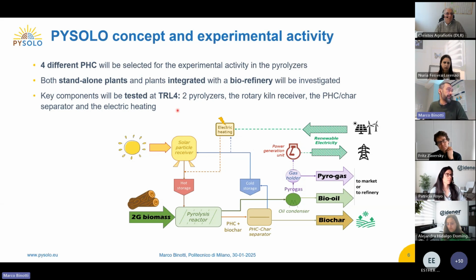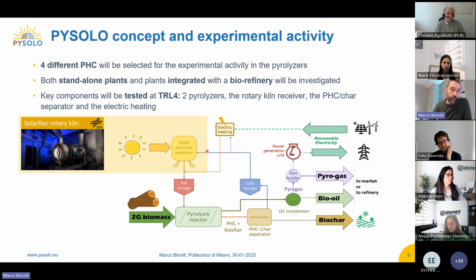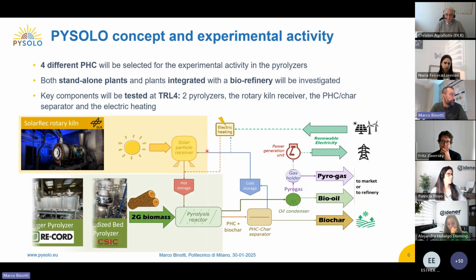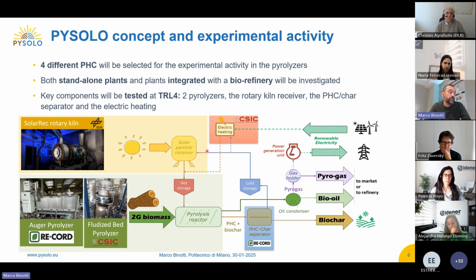So we will test 2 pyrolyzers, a rotary kiln receiver, the particle char separator, and the electric heating. The receiver system will be a rotary kiln receiver tested at DLR. It will have a power in the order of 15 kilowatts, and it will allow the use of particles directly within it. For the pyrolysis, we will have 2 different types of reactor: an Auger reactor, so a screw reactor, and a fluidized bed reactor. The electric heating system and the particle char separator will also be tested. The separator is an important component.